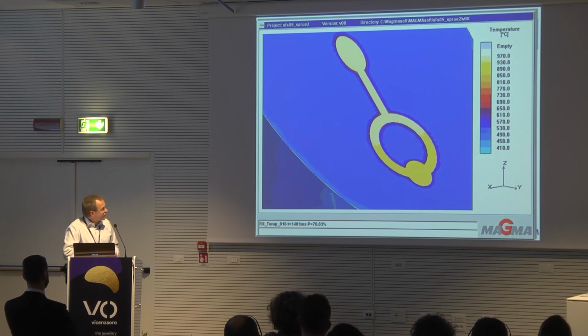So it's a cross-section in a simulation through the flask. This is part of the main sprue. This is the feed sprue. This is the item that we cast. If we let the metal flow inside, you can see everything here is at high temperature now, about the pouring temperature, and the blue color here is the investment material that surrounds the as-cast part.